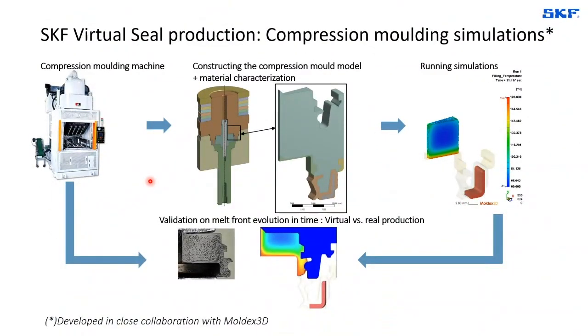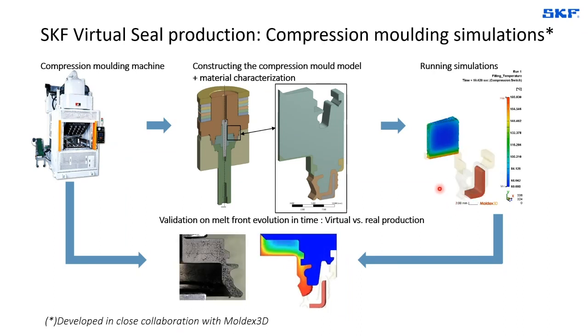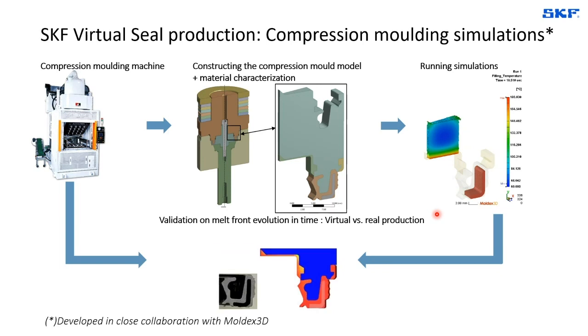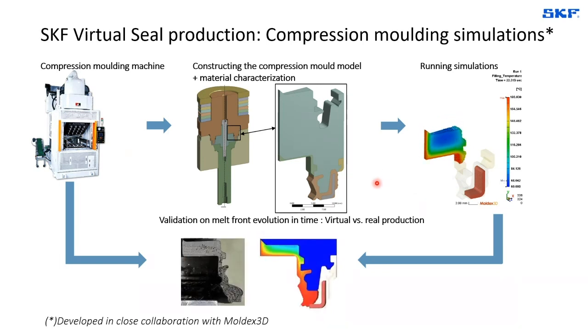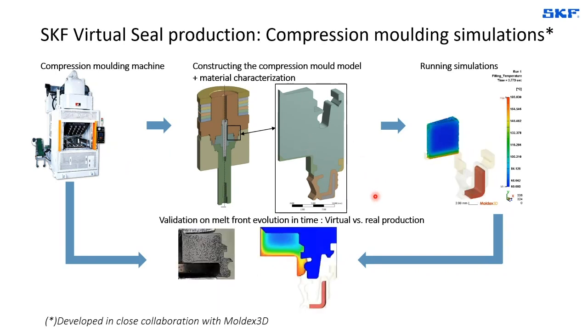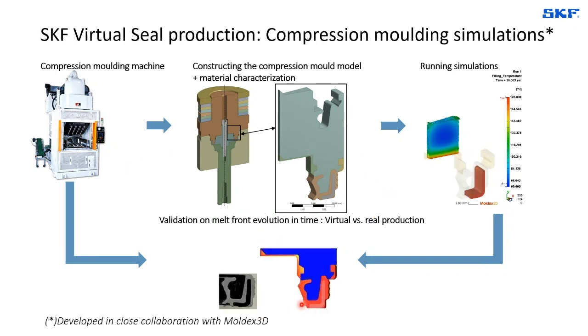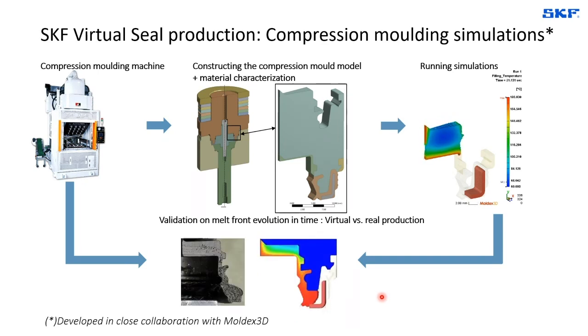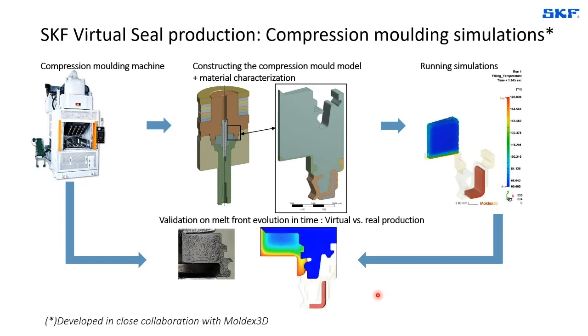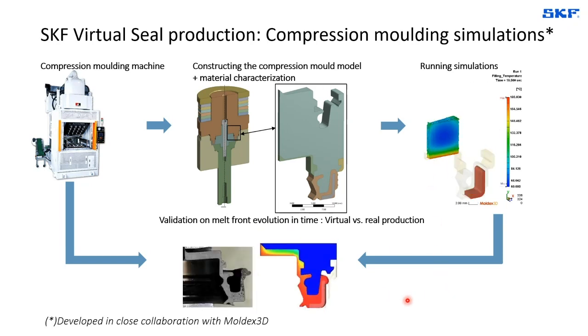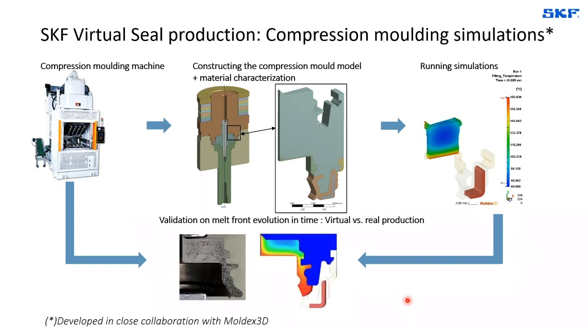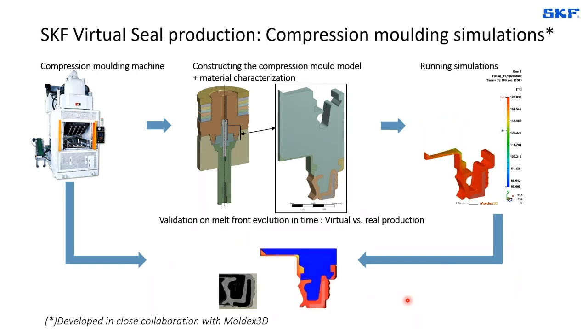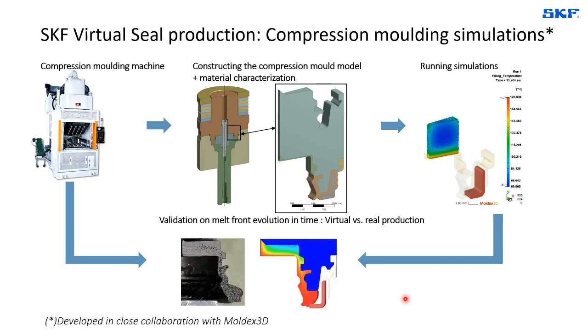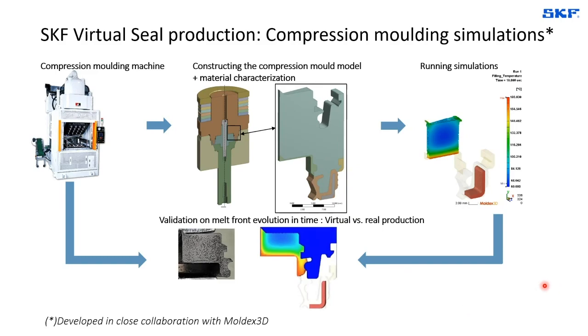Similarly, but more challenging, we also have the capabilities to predict the compression molding process in the same manner. We are able to predict the melt front, but also different types of potential defects and potential challenges in application. This was somewhat more challenging, and we had to collaborate with external parties, and we are today very happy to have these capabilities, which, as we can see here, are now in quite good agreement with the actual physical experimental behavior. Because the challenge in compression molding is that we are moving across different phases from solid to fluidic back to solid, and it is somewhat more complex to understand and physically model compared to an injection molding process.